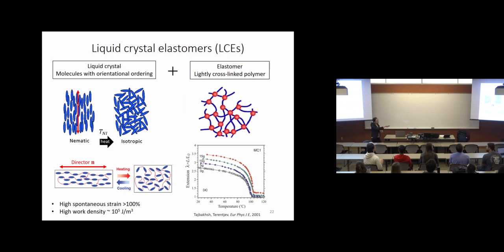Under low temperature, those liquid crystal rods align in a certain direction, and they can distort the polymer network into this ellipsoidal shape. This specific direction is called the director. But once you heat up this material, it can undergo the phase transition. Now the rods become randomly oriented, then it can relax the polymer network back to the spherical shape. Therefore, it can induce a large macroscopic shape change.